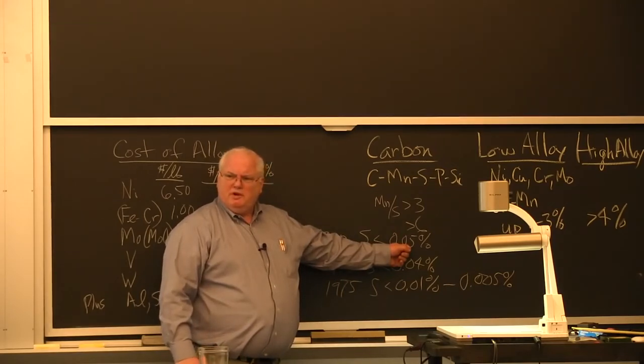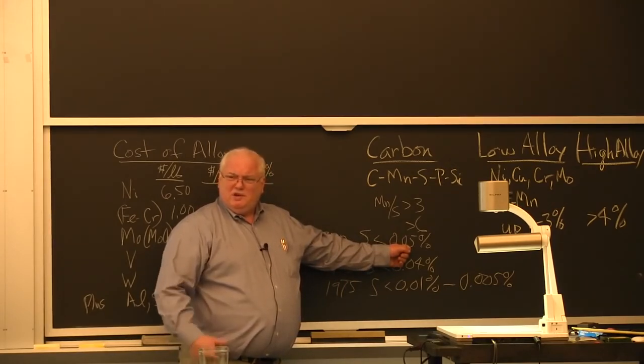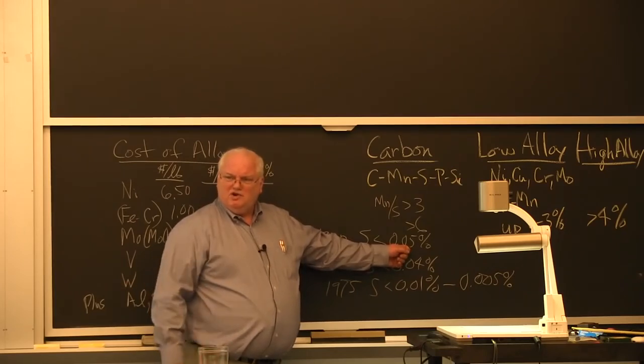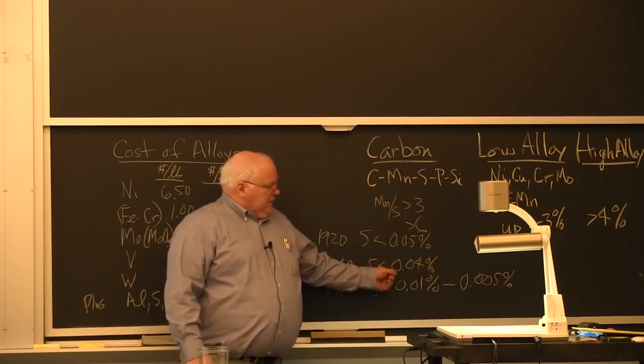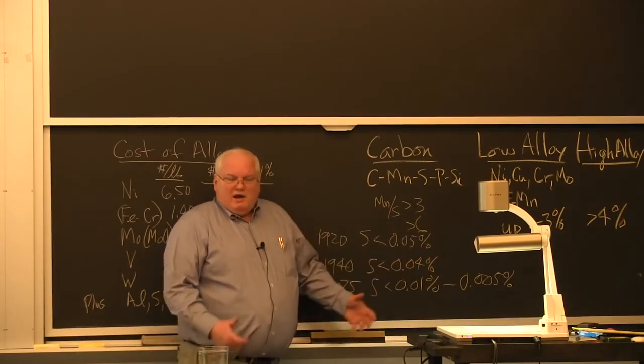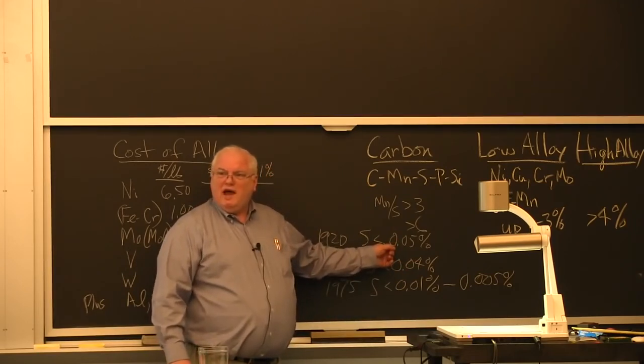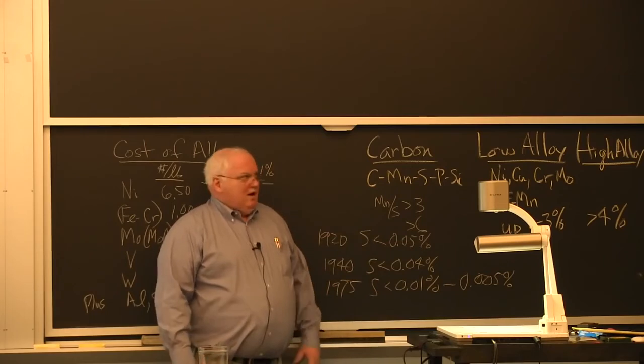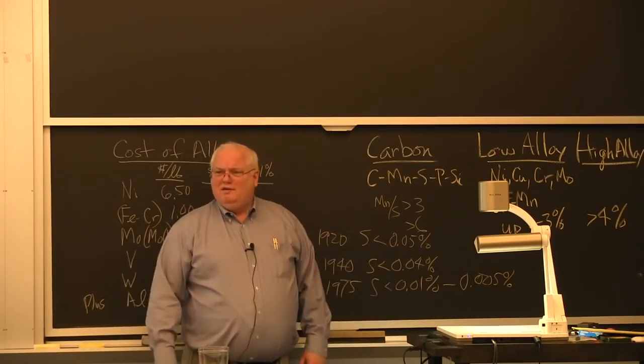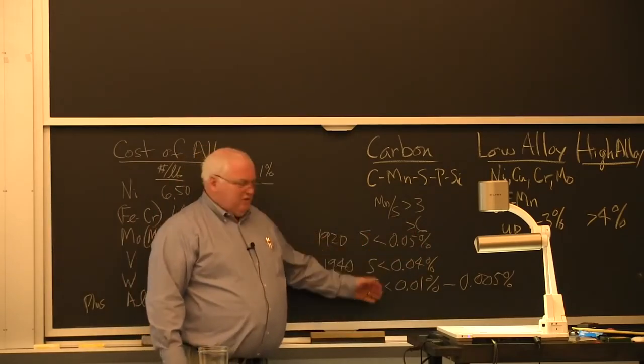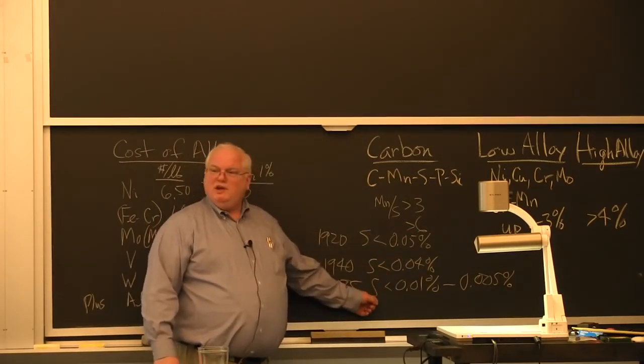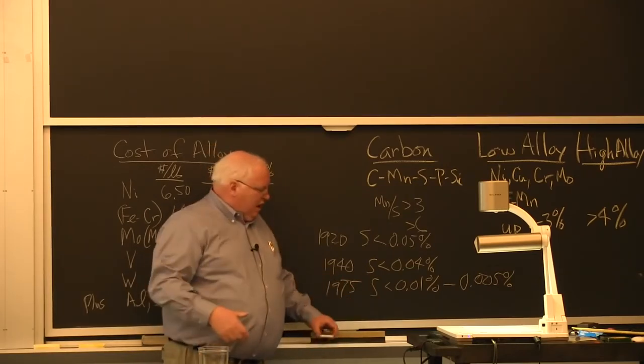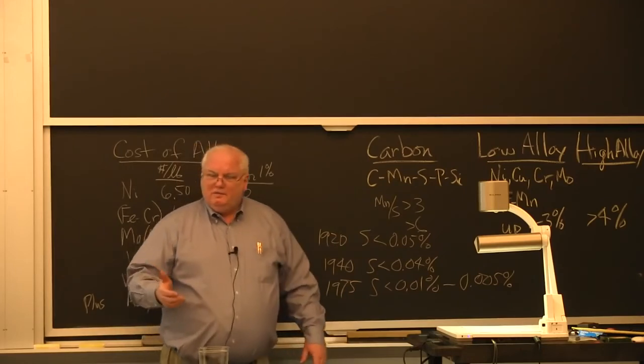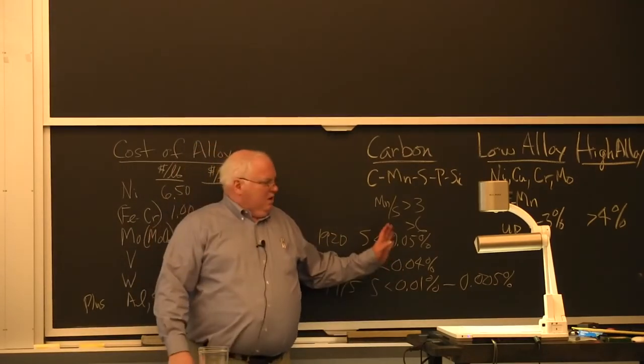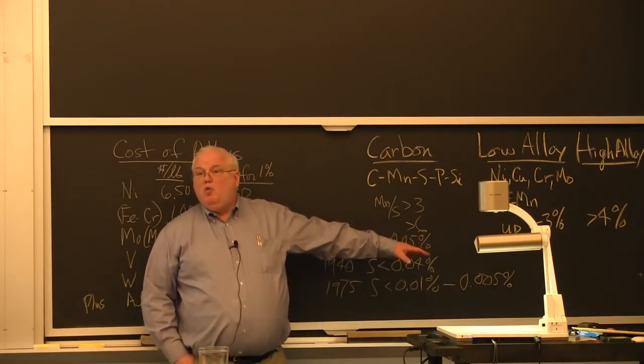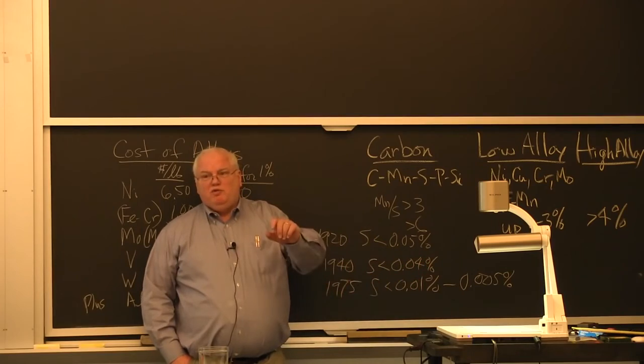0.05%, 500 parts per million, was about the best they could do in the 1920s with any regularity. They didn't know how to control it until John Chipman told them what types of slags and stuff to use. By the 1940s, you'll see 0.04. I can go to an ASTM spec and look at the spec, and they'll still have today, say the sulfur has to be less than 0.05. Are you kidding me? No one makes a 0.05 steel anymore, okay? They haven't made it since before 1950. They got to this, and then they were getting to very low sulfur. Sulfur does a lot of bad things for toughness and other things in the steel, but we've learned how to make it better and better. We can regularly get down to 0.002 or 0.001 sulfur today if we want, but we don't usually need to.